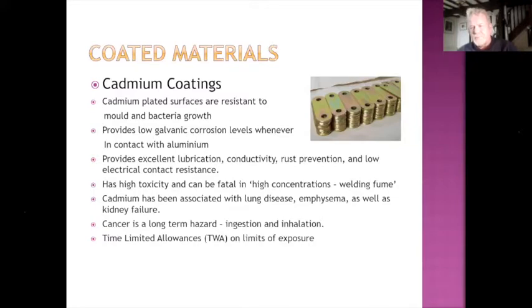So if you're going to put something onto a cadmium coated plate, the area where the weld is going to be carried out must be ground clean of the cadmium coat, and it should have a clearance area sufficient for the process that you're using. If you're using something like a MIG or TIG process, at least 12 mil all round the area where you're going to be welding, so that that doesn't progress. You need to be aware of the heat buildup because the conductivity could give some problems, but generally that should be okay. But again, local extraction wherever possible.